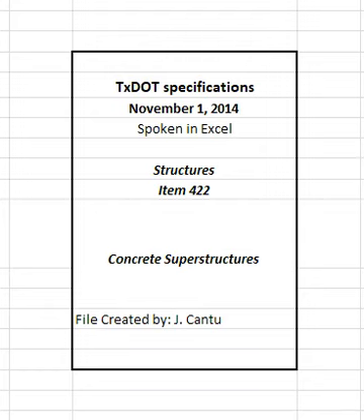Completely fill the void between the hole and dowel or bolt with grouting material. Follow exactly the requirements for cleaning outlined in the product specifications for pre-packaged systems. Provide a Type 1-2 epoxy per DMS 6100, Epoxies and Adhesives, when neat epoxy is used for anchor bolts or dowels. Provide Type 5-3 epoxy per DMS 6100, Epoxies and Adhesives, when an epoxy grout is used. Provide grout, epoxy, or epoxy mortar as the binding agent unless otherwise indicated on the plans. Provide other anchor systems as required on the plans.